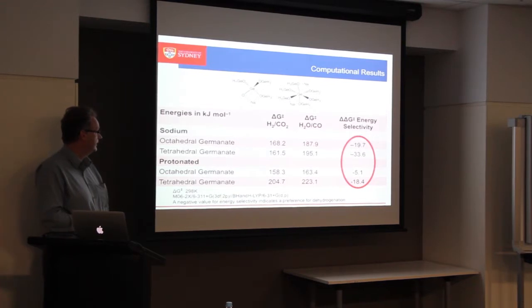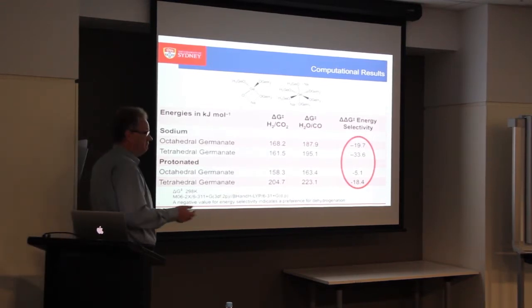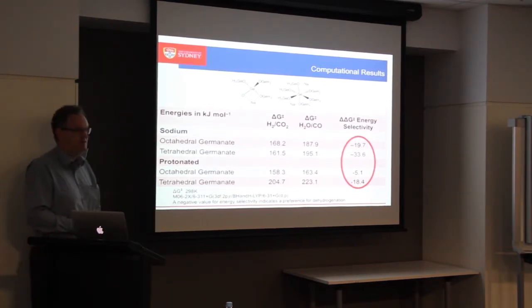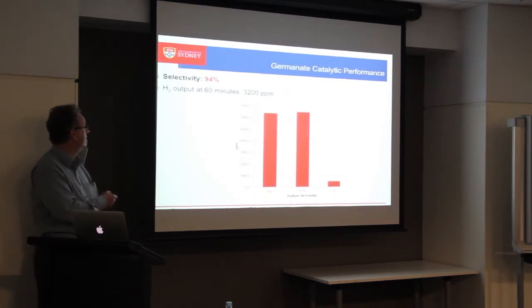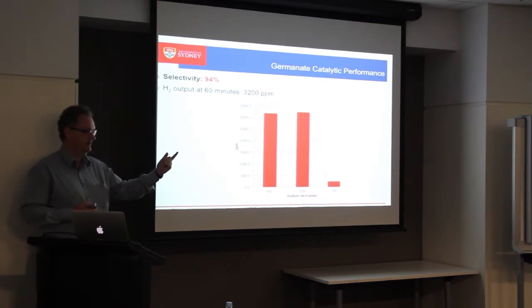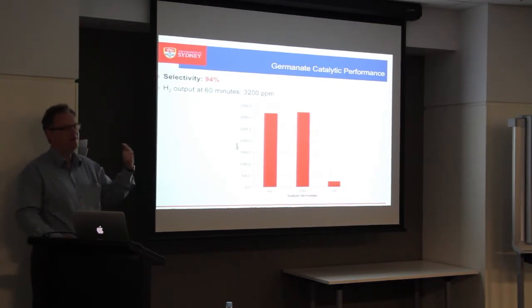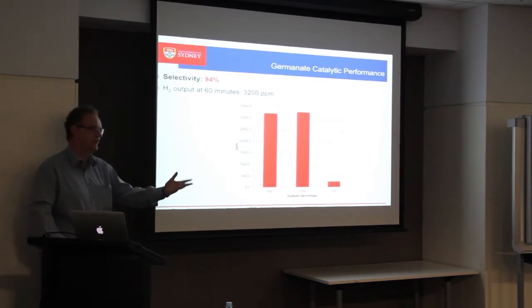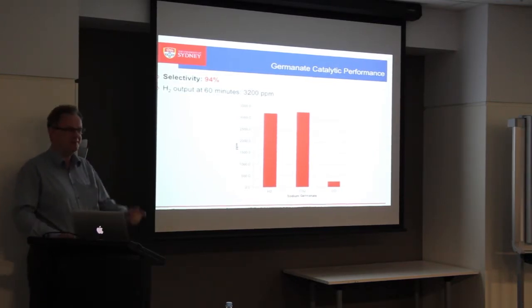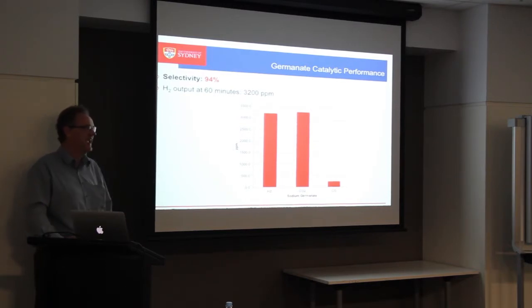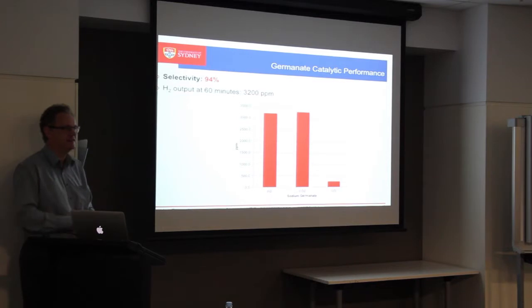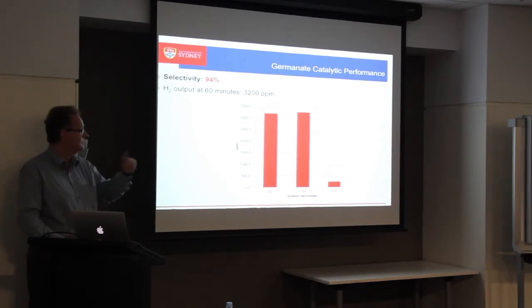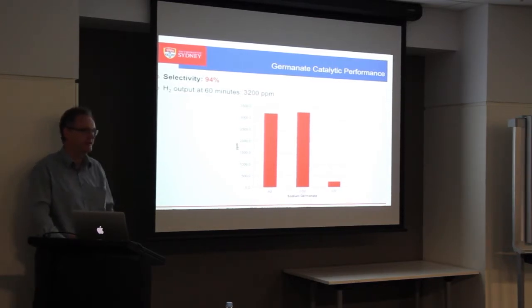They should all be selective — right, there you go. And we have the kit, so let's see what happens. Lo and behold, we get 94% selectivity in the direction we want. No way in the world would we have taken potassium germanate and said, oh, well, that might work. You might as well take any random oxide and say that won't work. So it's really come from doing these things carefully and with communication.